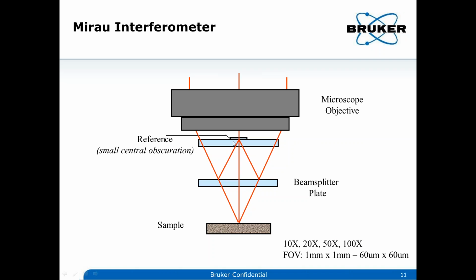So you have a beam plate here, and then another one with a mirror here. It's a very small mirror. Compared to the field of view, it's negligible, so it doesn't affect your measurements really. So you have this kind of technique, and you can go up to 100x in this. There's another technique called the Linnik interferometric objective, especially for ultra-long working distance experiments. So for most applications, these two would be sufficient.